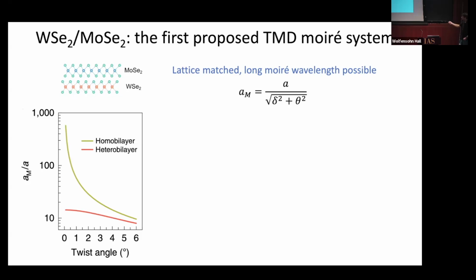On the other hand, for lattice matched compounds, so here this is an image I took from a review article from the Cornell group. They labeled it as homobilayers, which obviously will have the same lattice constant, but actually this molybdenum tungsten diselenide combination also has a very, very similar lattice constant. So as you decrease the twist angle, you can get to very long Moiré wavelengths. And in particular, I want to emphasize this low twist angle regime is the regime in which the ratio of the Coulomb interaction U compared to the hopping T is the largest. And so going to lower and lower twist angles helps you get to this most strongly interacting limit.